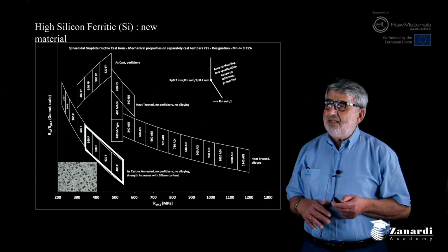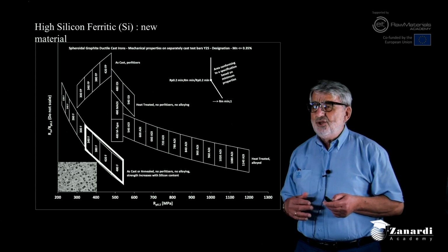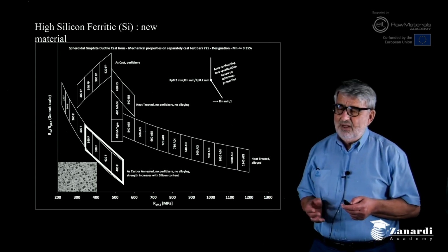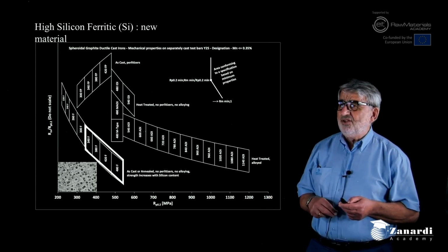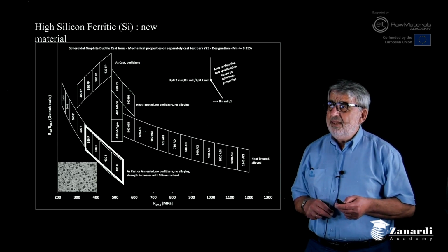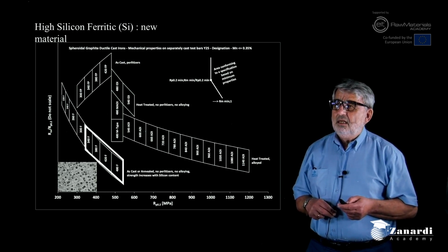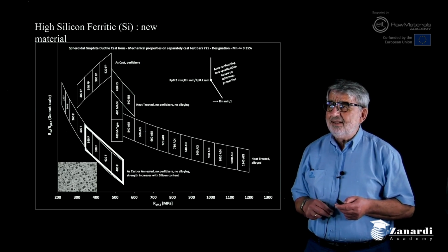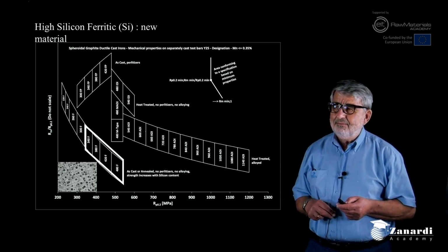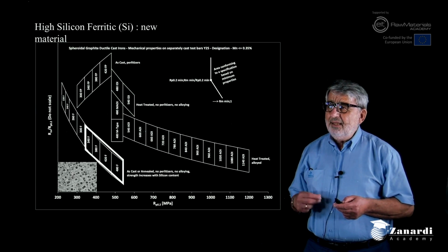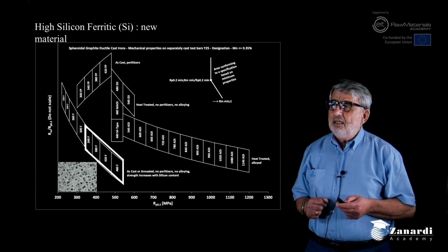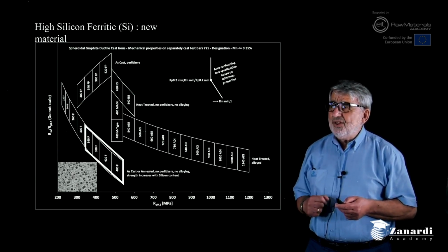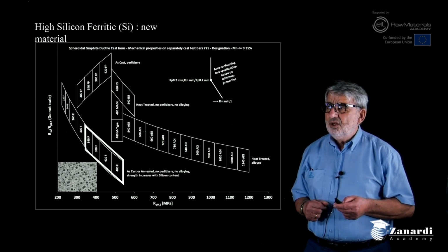And even if these grades show a very attractive elongation at the fracture, they are very sensitive when the triaxiality state is increasing. And this is given by the low strength ratio they have.